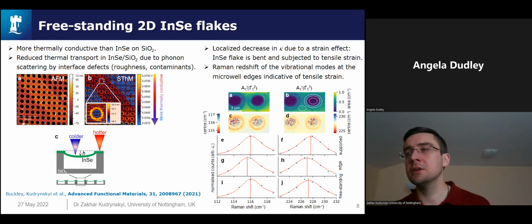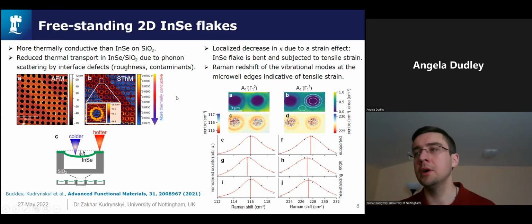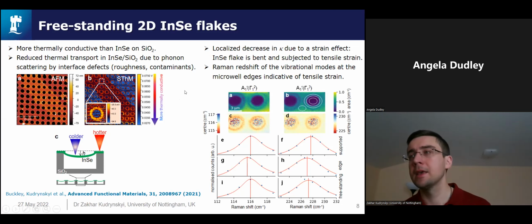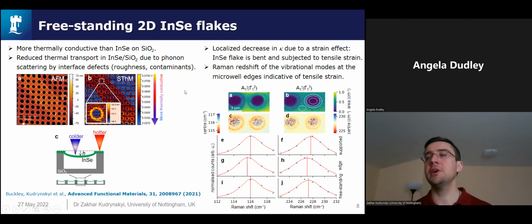This assignment is confirmed by our micro-Raman spectroscopy studies, revealing a Raman redshift of the vibrational modes at the microwell edges. Previous studies showed that tensile strain in bent indium selenide can shift these Raman modes and enhance anharmonic phonon scattering, reducing phonon group velocity and heat capacity.